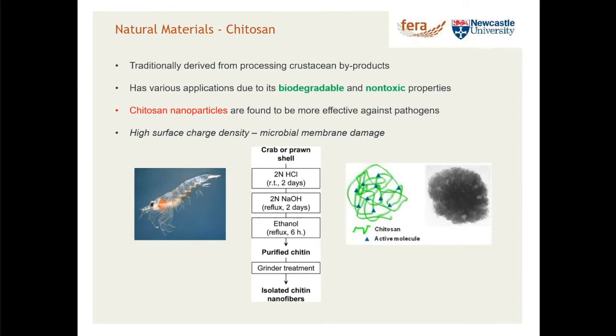And one of the added properties is that not only does it provide the basis of barrier materials, but it also has an inherent sort of antimicrobial activity as well, and even antifungal. And there's been recent publications which have nicely demonstrated that these materials damage the membranes of things like bacteria, the cell walls are disrupted, and that's the mode of action. So we get an added benefit. If we could exploit chitosan for packaging, we'd have quite an interesting potential alternative.